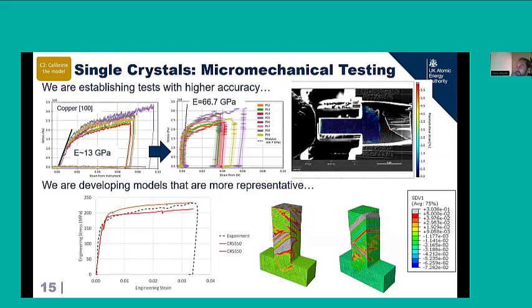So the conventional way of doing things is to trust in the indenter displacement. But if we were to do that, we would measure a far more unrealistic elastic modulus, and therefore other properties, compared to having this correction. And then in linking with that, calibrating models, we're developing the constitutive equations to provide for much more representative simulations in terms of the strain heterogeneity and the stochastic nature of slip at the single crystal grain scale.